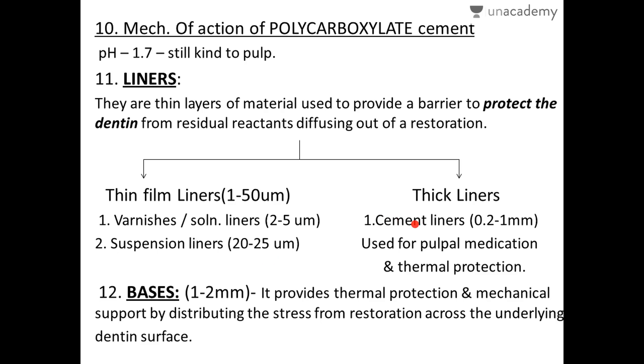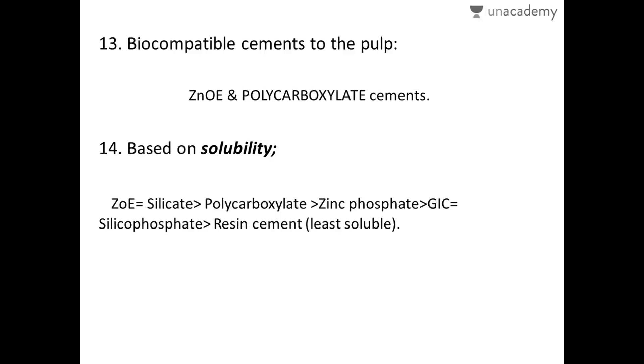Thick liners are cement liners with size varying from 0.2 to 1 mm, used for pulpal medication and thermal protection. Bases are measured from 1 to 2 mm and are thick layers beneath the restoration providing pulpal medication, thermal, and mechanical protection. Bases distribute stress from the restoration across the underlying dentine surface, so the whole tooth including the periodontium shares the occlusal forces.